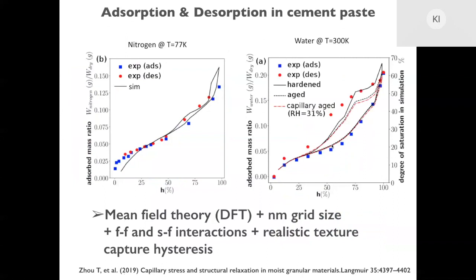One more thing that we did is that once we have the distribution of water, as I told you, we can then relax the structure, so see how the solid matrix will change, and then repeat the adsorption. This is like when people in experiments do multiple cycles of adsorption desorption. You can see this, we did it for water. For nitrogen, there is no big difference, but for water, it's the two lines that are on top. So basically, the hysteresis is reducing a little bit because we have a better packing of the cement grains.